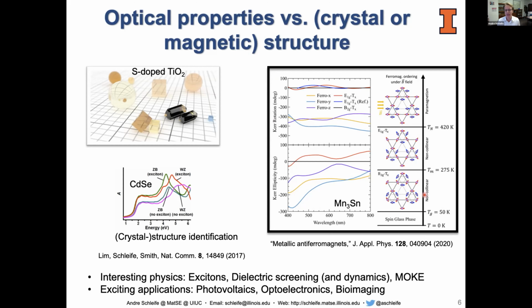So we started with the phase that appears at slightly higher temperatures, which is a non-collinear antiferromagnetic phase. And then at even higher temperatures, you see a phase transition to a different non-collinear antiferromagnetic phase. And we computed optical, in this case, magneto-optical properties, actually Kerr rotation, and wanted to see if we can tell these different phases apart. It turns out that for the different antiferromagnetic phases, that's not so easy because typically the signatures are not so strong. If you were to make this material ferromagnetic, the signature is much larger.